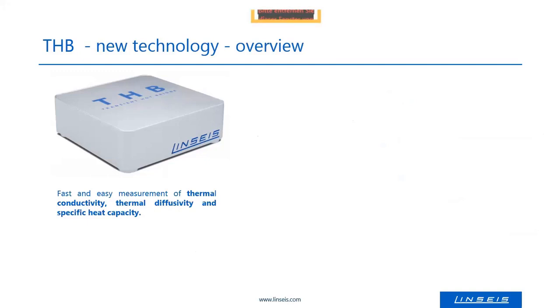A transient hot bridge, as I told you already, is a hot wire technique. And the good thing with hot wire technique is that you get directly as a result the thermal conductivity. That's not the situation for the optical methods, for the laser flash, for example. There you get the thermal diffusivity as a result and not the thermal conductivity. But also for the THB, we can measure the thermal diffusivity. And if we know the density of the material, from the thermal conductivity and diffusivity, we can calculate also the specific heat capacity, which is quite a useful information.